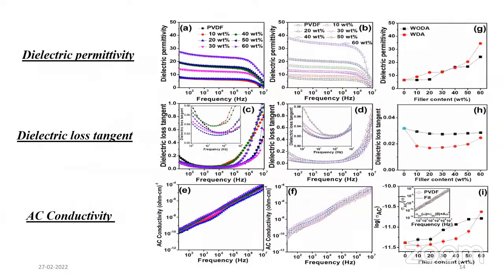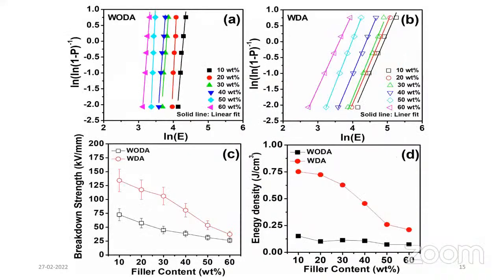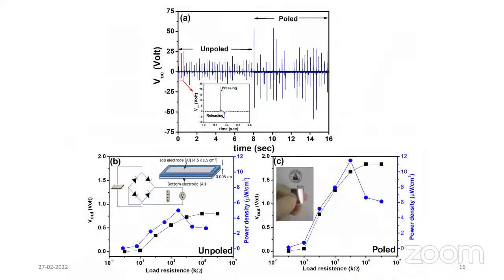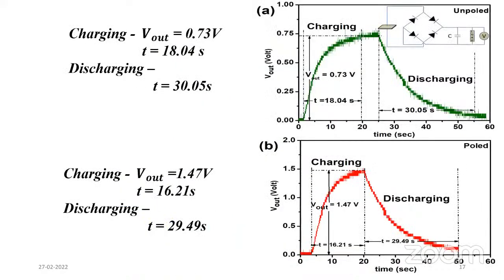Now these are the dielectric permittivity graph, dielectric loss and tangent graphs, and AC conductivity graph. And these are breakdown strength related to filler content and energy density related to filler content. The results with dopamine added show very great properties in comparison to those without dopamine. Now these are the graphs of the device which was poled and unpoled. After poling, the device gave better results, and these are the final results which I got.